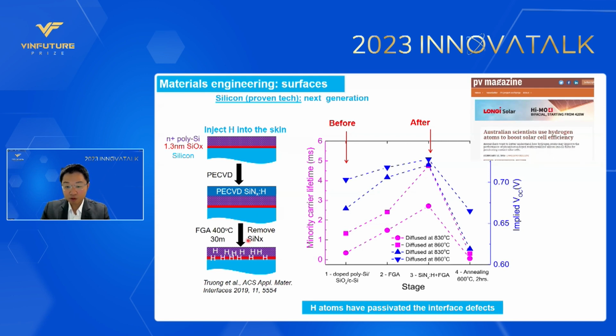The method is quite simple. First, we deposit a layer of hydrogen-rich silicon nitride. Then we put the sample in a furnace at around 400 degrees Celsius for 30 minutes. And during this step, atomic hydrogen from the silicon nitride film can be moved into the passivating contact structure. So with our technique, we can see a big improvement in the performance of our samples.